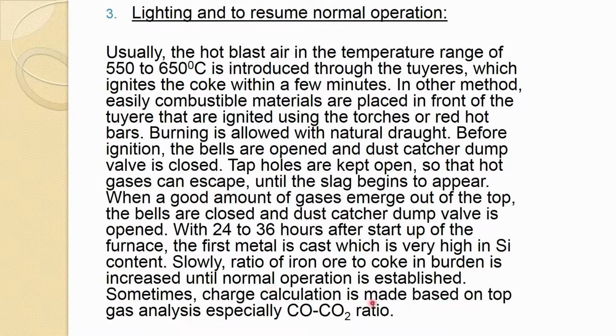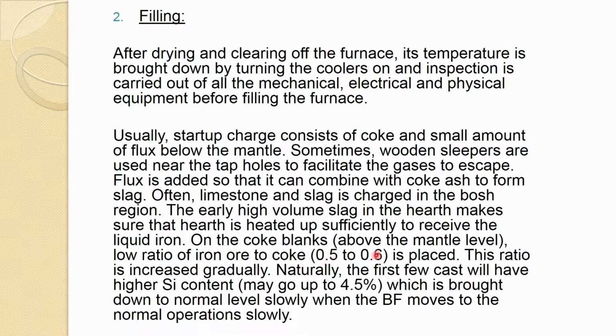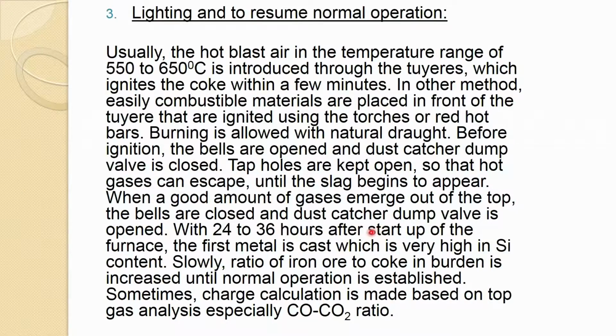Sometimes the charge calculation is made based on top gas analysis, especially the CO/CO2 ratio. As we mentioned in the previous slide, the ratio of iron ore to coke is 0.5 to 0.6, and slowly you increase it in steps of 0.05 or 0.3 sort of ratio. Another way of doing it is to analyze the CO/CO2 ratio, and based on that you can